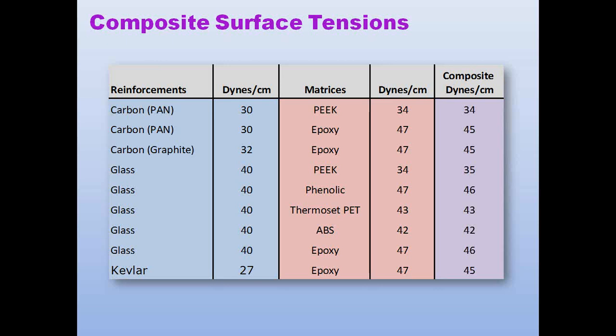As we see more of these materials, we have to take note of the fact that it's the matrices that make up these materials that are the main determinant of what the ultimate composite surface energy is. So even though we recognize that, for instance, a carbon fiber reinforcement inside of a PEEK, or polyether ether ketone, matrix may be heavily populated with these carbon fibers, it is primarily the matrix material that will determine how we functionalize the surface of the material for adhesion to another composite or another virgin material.